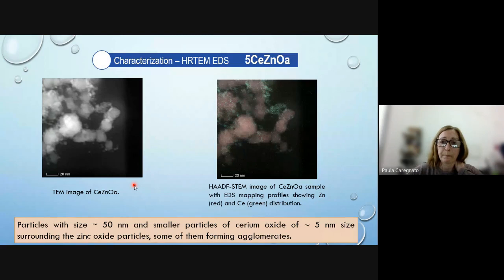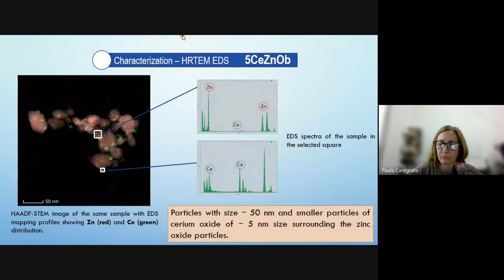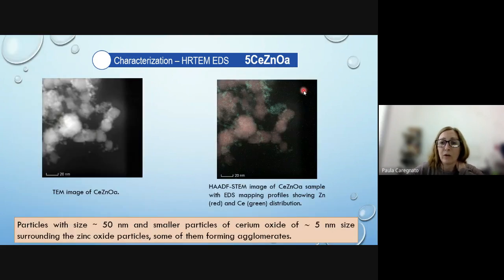I'm not sure, but I would say that this TEM image is of this material, 5-cerium zinc oxide basic. For 5-cerium zinc oxide acidic, the EDS mapping profile in TEM microscopy is quite similar to the one I showed before. We have big particles of zinc oxide and smaller particles of cerium oxide, which were surrounding them and in some cases forming agglomerates in the sample.